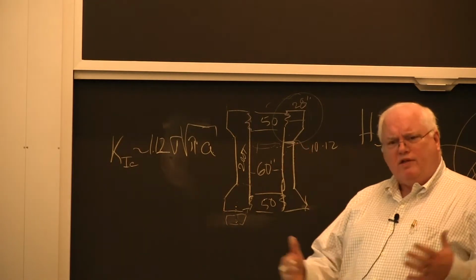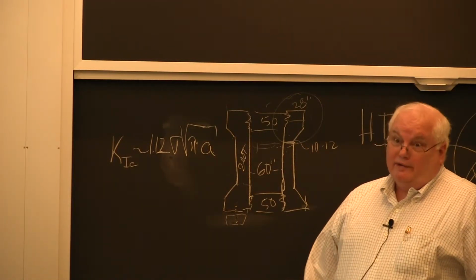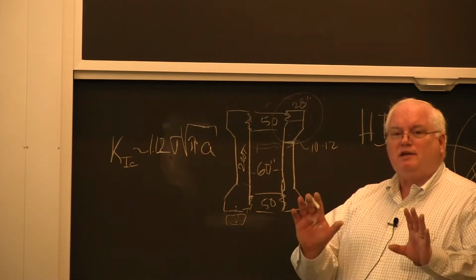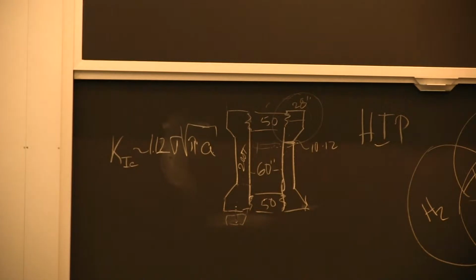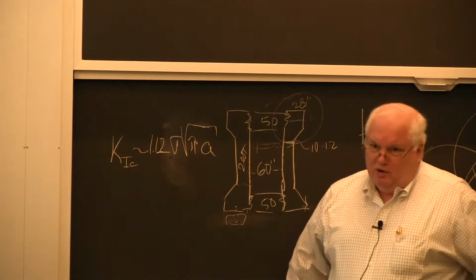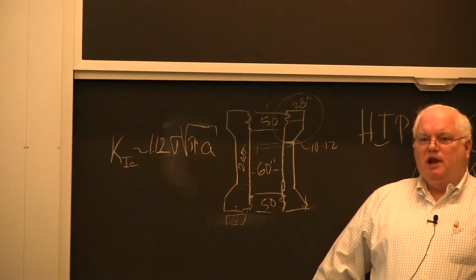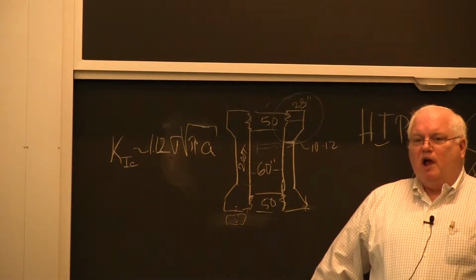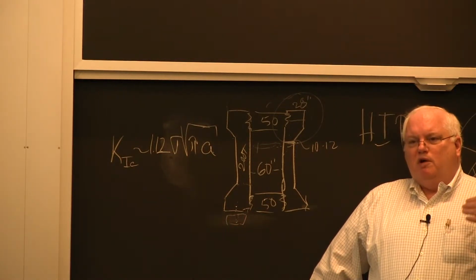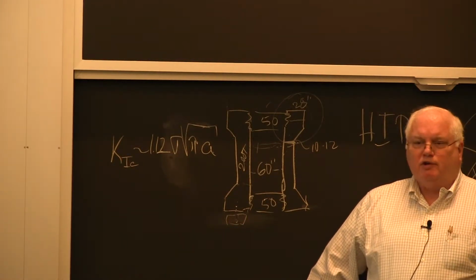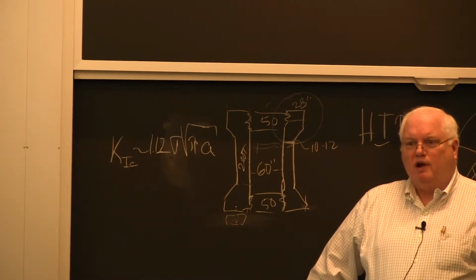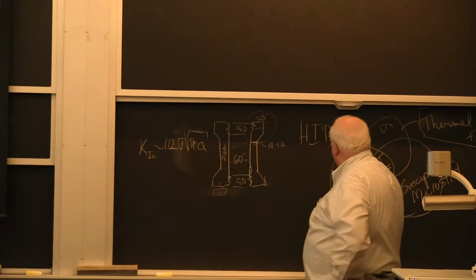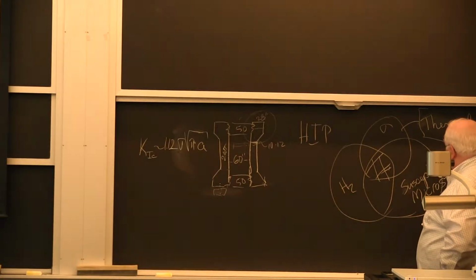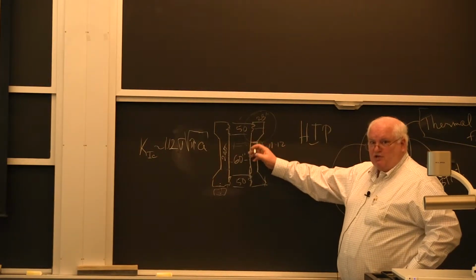And in fact, everybody said, "Why did the crack start on the outside?" I said, that's where the thermal stresses were highest. This was transient thermal stresses. They had never done that in the Cray computer because it was too big a problem in 1982 or whenever they were designing this. There were not computers powerful enough to worry about the transient heat flow analysis. Nowadays, get yourself a good PC and you can do it with a finite element program. But they couldn't do it back then. So they had too high a stress that they had never calculated. It was under high stress, the maximum service stresses, plus the thermal stresses, which they hadn't accounted for.